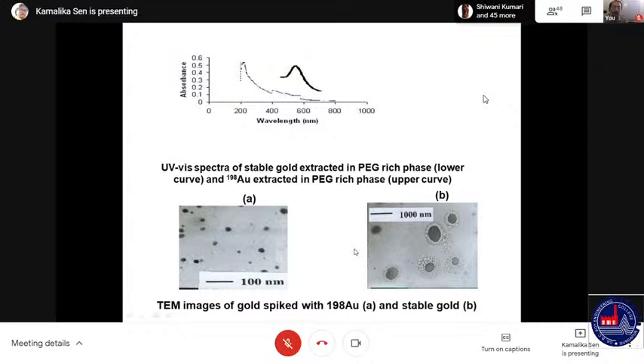Here, I would like to mention that after this pink color incident, our radioactive gold, which was brought from BARC, was also decayed after some 1 month or so. So my experiment was over, and I could not do any further experiment. I thought, okay, if gamma is the responsible thing, we have a gamma chamber in our institute. Saha Institute itself had a gamma chamber at that time. So I prepared my sample solution and put it inside the gamma chamber so that gamma radiations would make my nanoparticles. But that was a failure. That did not prepare the nanoparticles. Later on, I will come to it.